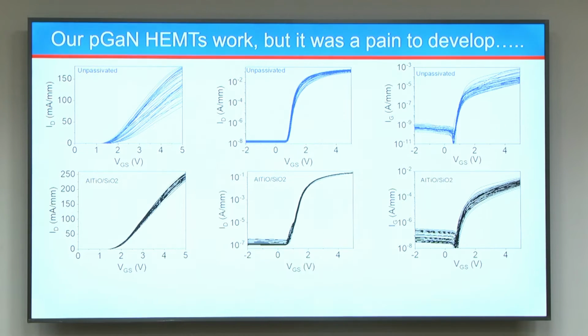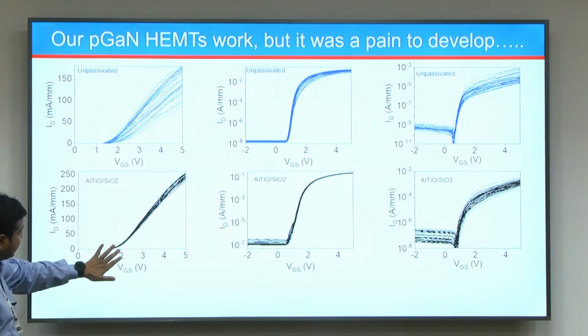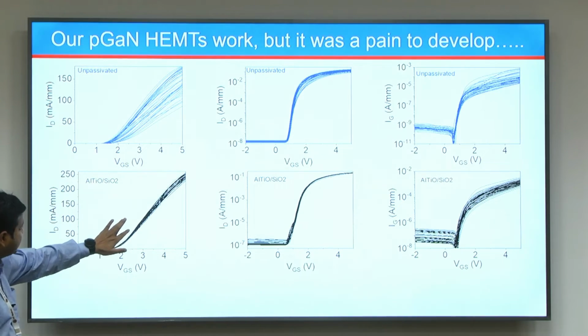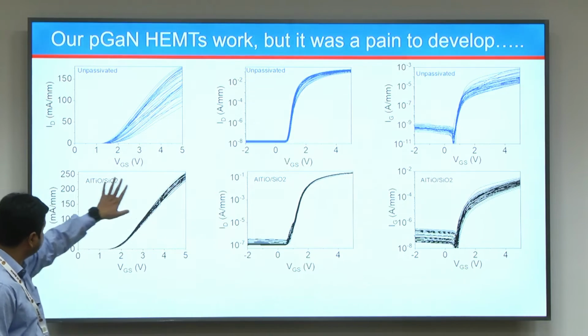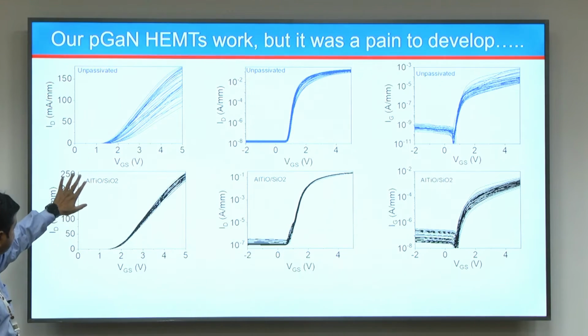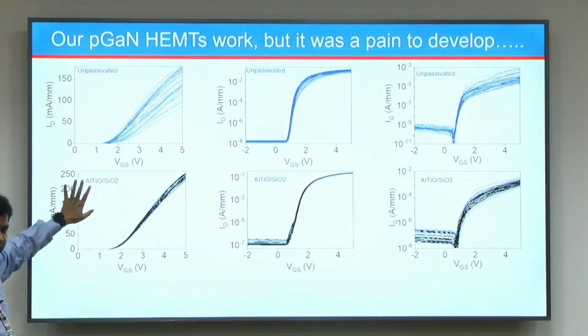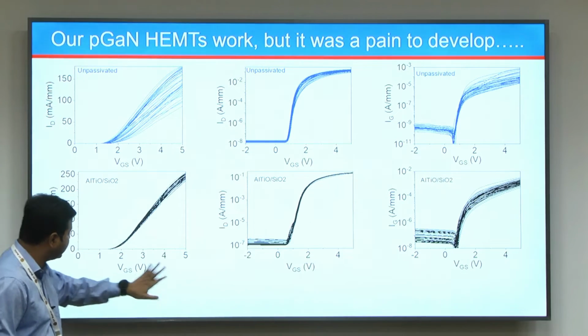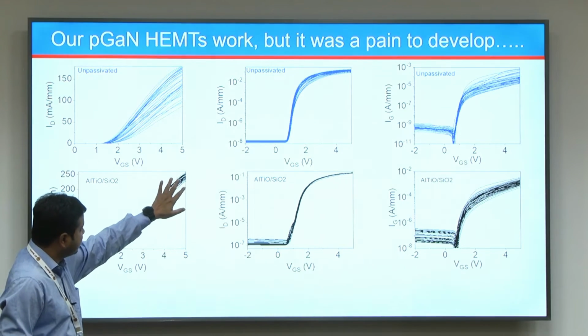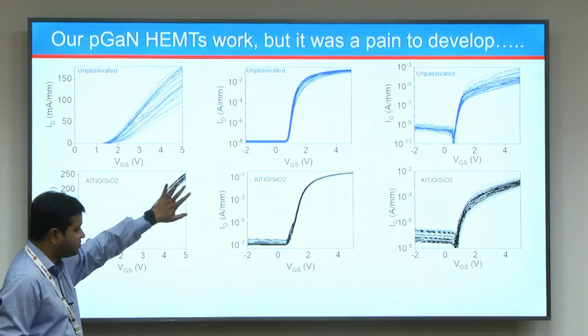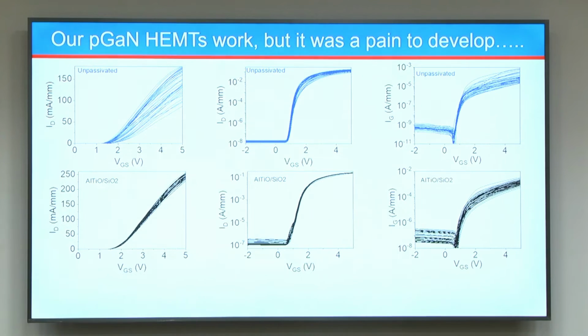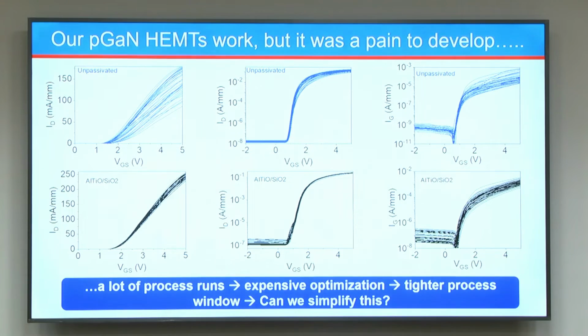So finally, we have the technology. We have these pGaN gate based E-mode devices, and as you can also see, the variability across the wafer is quite negligible. We are in the range of 250 milliamp per millimeter kind of a drive current at a gate voltage of 5 volt, where if you see data across 150, 160 devices, the variability is within plus minus 10%, right.